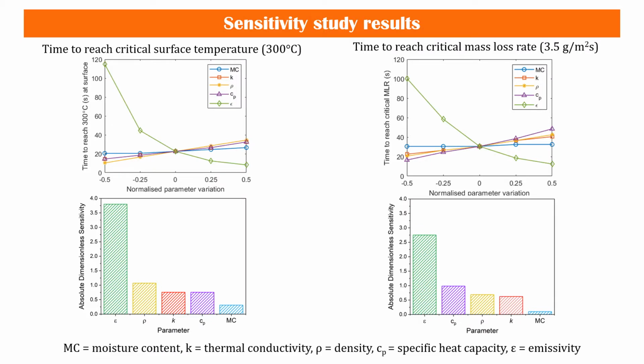A sensitivity study was conducted to find out which material properties the time to ignition is most sensitive to. The times to reach two ignition criteria were investigated. These were the time to reach the critical surface temperature of 300 degrees and the time to reach the critical mass loss rate of 3.5 grams per meter squared per second.